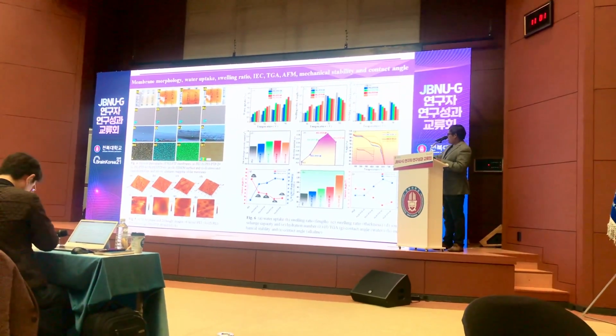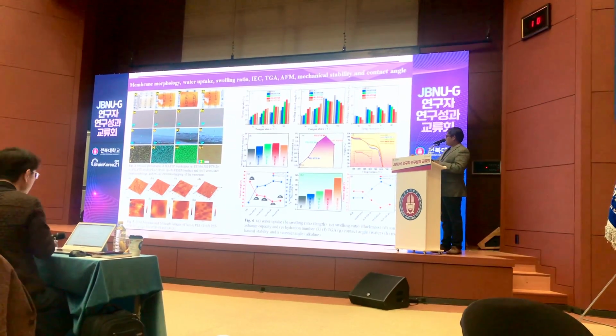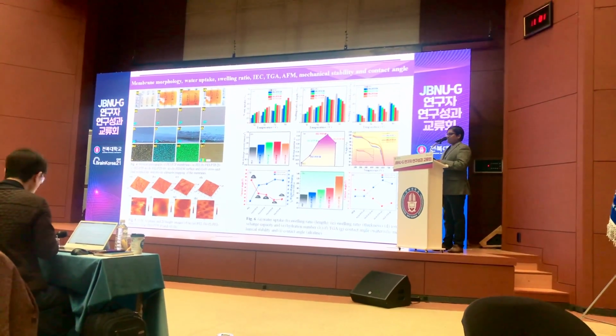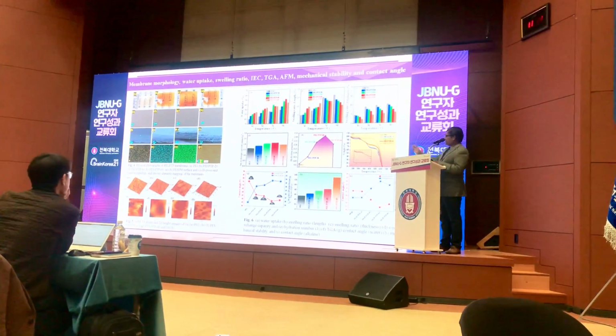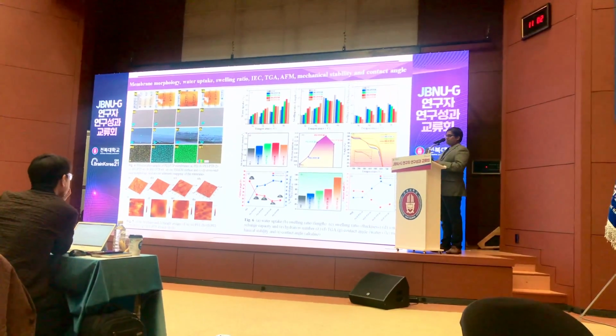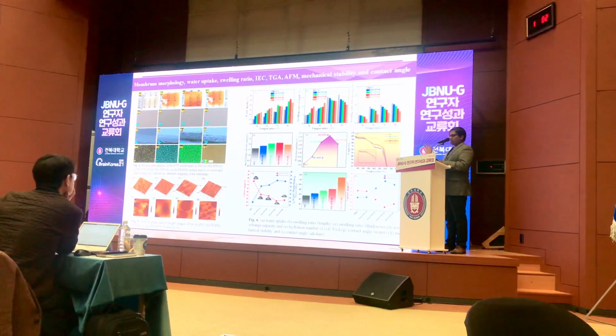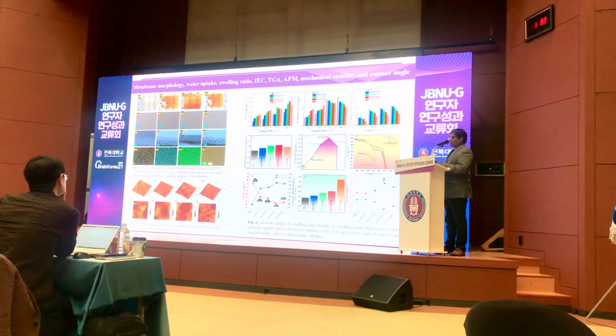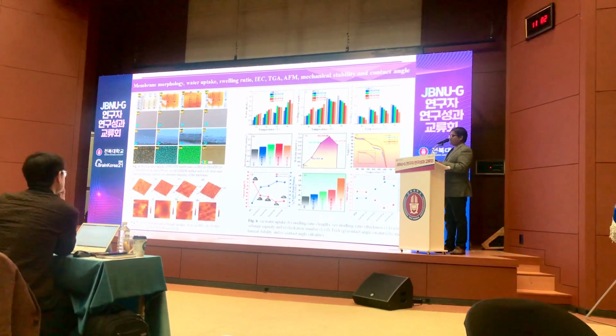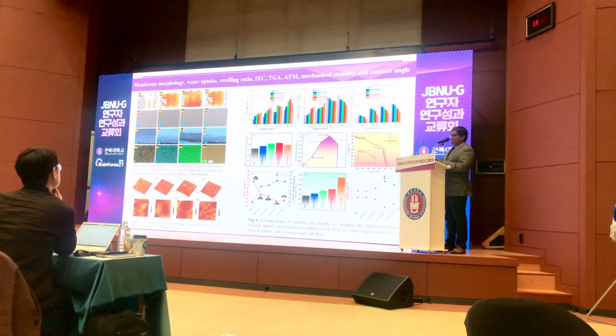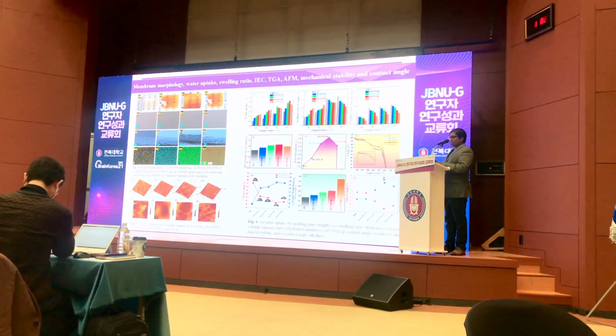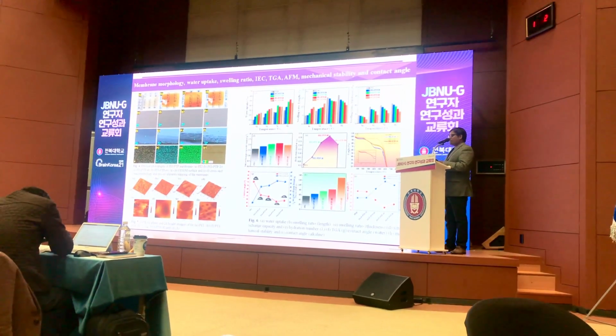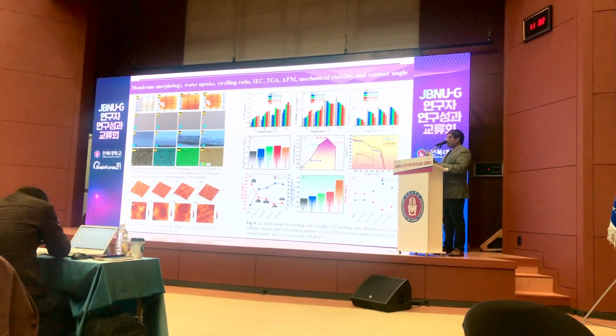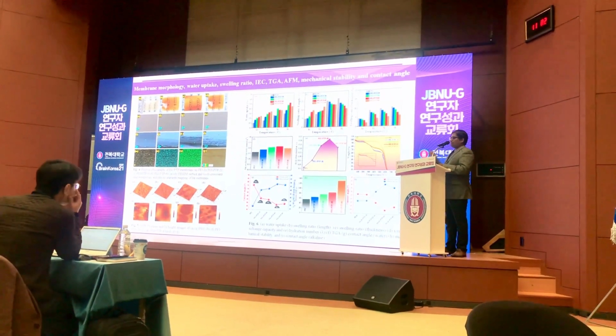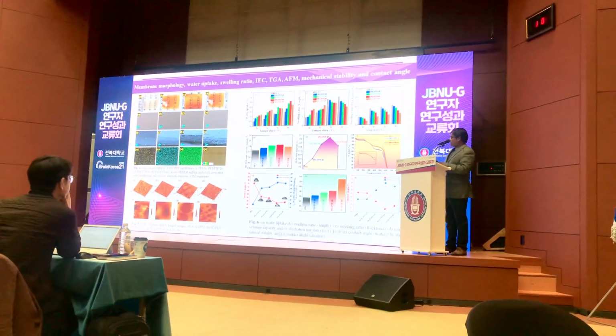TGA shows that up to even 100 degrees, 200 degrees Celsius, there is no mass change. The initial mass change might be just moisture. So we don't have to worry about thermal stability in my invention. And then finally, contact angle and water uptake are almost the same. If you have a very good contact angle, it means the electrolyte is hydrophilic, not hydrophobic.